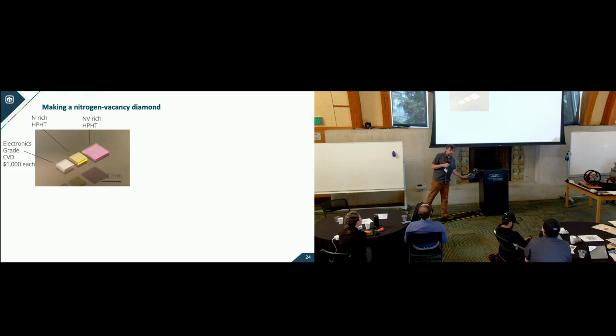Perhaps I should have put this slide before this one, because this is our starting material. Typically we start with electronics grade diamond for these kinds of experiments. You can buy this from a company, well, it's through Thorlabs now, but it's Element Six, a subsidiary of De Beers, that sell the highest purity diamonds. They're like the only people that sell those. And a 2 by 2 millimeter plate, 500 microns thick, is almost $1,000 these days. Now this is the CVD grown version.